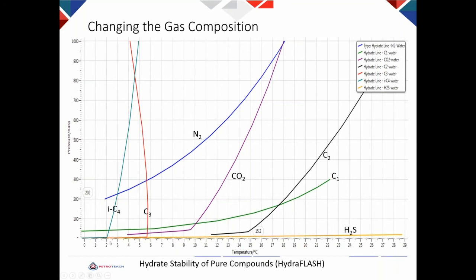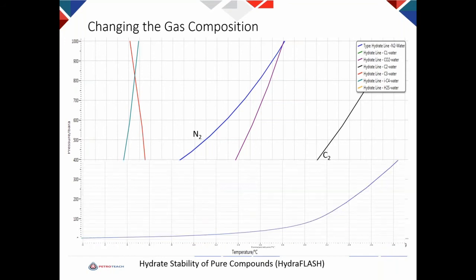After that, isobutane, then propane. Then you can say CO2 and C2. This is then methane, and this is nitrogen. You see that nitrogen is the weakest hydrate former among the gas components we have in the reservoir. So if you have a reservoir fluid, the example we put last time was 85% methane, 5% ethane, 4% propane, and the rest. The hydrate phase boundary of that gas is this one.